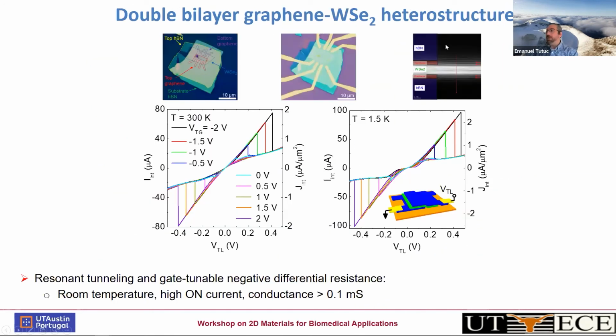So this is the heterostructure. This is a transmission electron micrograph. This is a sample that we've sacrificed. You see here bilayer graphene, transition metal dichalcogenide. Those are the outlines of the layers. And then we'll pattern contacts to the individual layers using e-beam lithography and metal deposition.